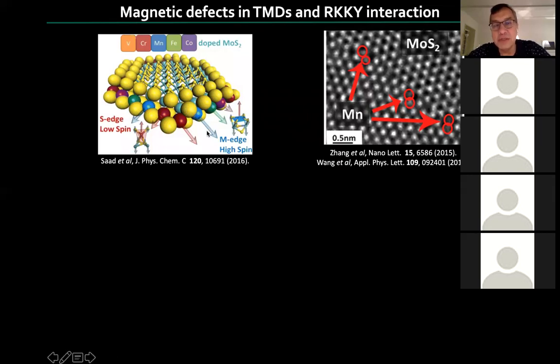You can imagine that, of course, one interesting target will be to dope these materials with magnetic atoms, because you can create a magnetic semiconductor. And there are various reasons why they will be interesting. People have actually tried, with various degrees of success, to incorporate magnetic atoms, right? Vanadium or chromium or manganese or whatever. Here is a picture from the group at Penn State, where they incorporated manganese in molybdenum sulfide. It is apparently hard to have a very high concentration of manganese because of chemistry, but it's possible.